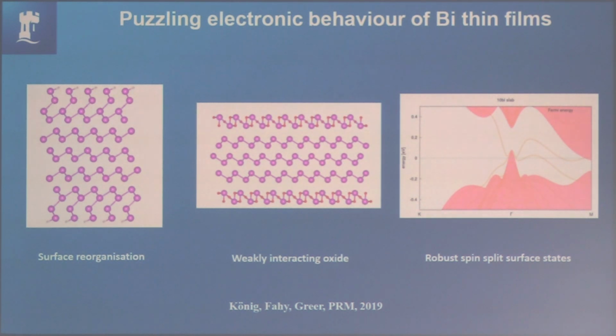But this is where spin, I said I'd mention spin. They're kind of cool because they arise from spin-orbit coupling. So this band here will have spin up. It's only half occupied. And, well, it's fully occupied, but it's only a spin-up band. And this band down here is spin down. So it's quite an interesting effect, but they're very robust.